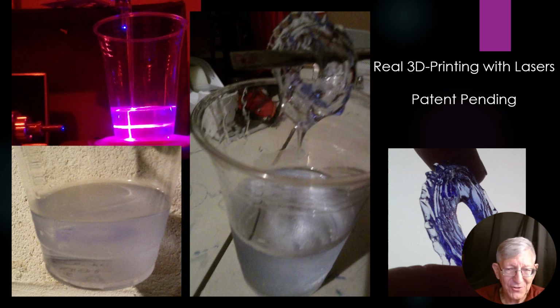And this allowed us to just go in with a probe, which we did in the center, and put the probe through the center of that donut, pull it out, and you see it draining off here. The liquid resin is draining off the solid. And then once we have cleaned this up, rinsed off the excess liquid resin with solvent and allowed it to solidify. This is actually an acrylic resin, and sunlight immediately solidifies this stuff. The liquid acrylic resins get pretty hot. The polymerization process is pretty exothermic.